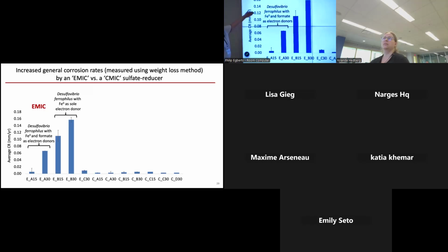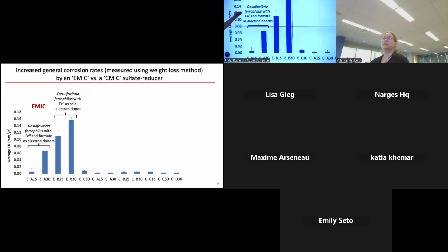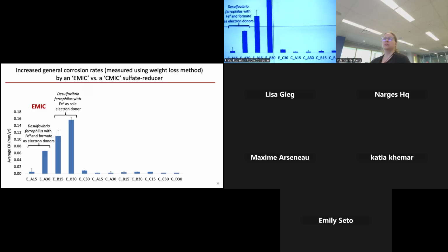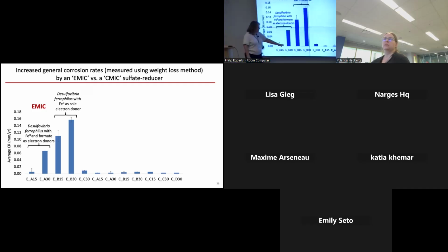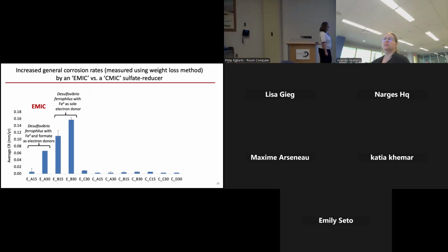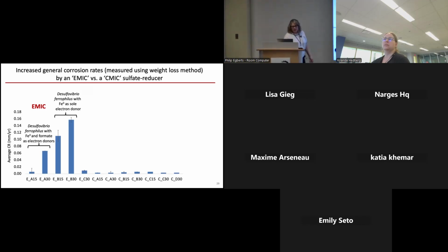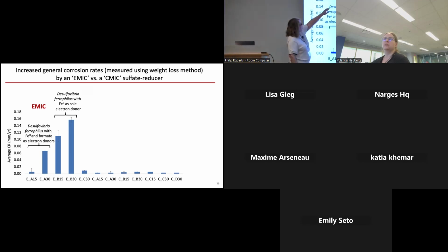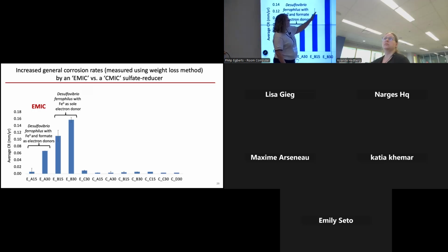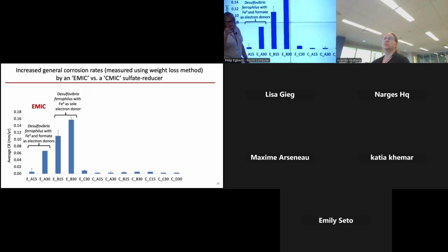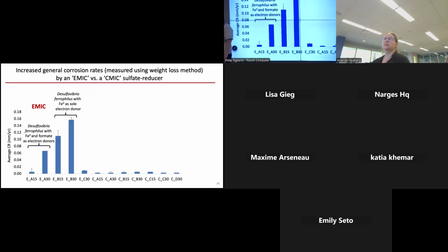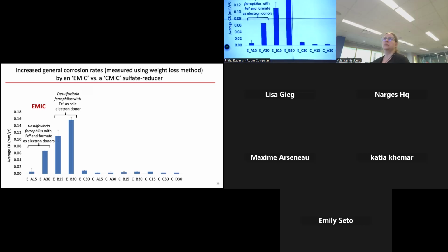This is a type of sulfate reducer called Desulfovibrio ferrophilus. Iron was the electron donor, but we also added formate. So when we had another organic carbon present, not just the metal, we had slightly lower corrosion rates. But here, iron was the sole electron donor, so we had higher corrosion rates. That really suggested that somehow this organism is taking those electrons right off the metal and facilitating a faster reaction from the metal.